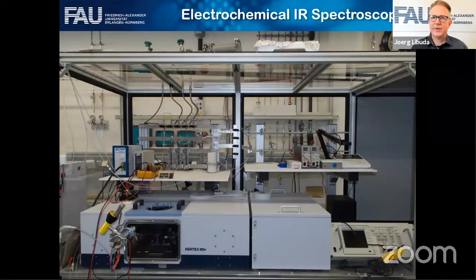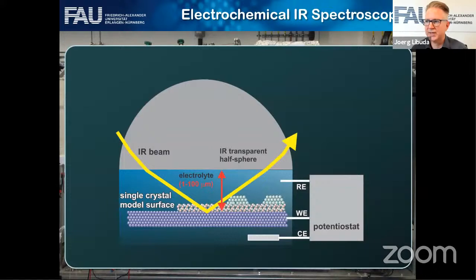Now, this is the structure. Next, let's take the next step and look at the chemistry. So how would you look at the chemistry? Vibrational spectroscopy is a very important method to look at chemistry. This is a picture of an electrochemical infrared spectroscopy system that we're using in our group. So how does it work? You use your model surface, exactly the model surfaces that I showed. You come in with your infrared beam through an infrared transparent window. And then there's a little gap in the micrometer range filled with electrolyte. You go through this gap, reflect your beam at the surface, and there you put your detector and measure how much of your infrared radiation has been absorbed.